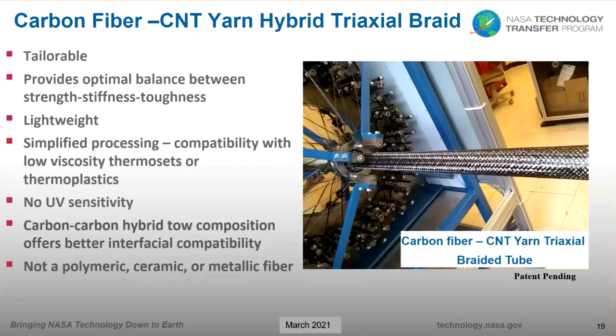My initial concern, my biggest concern with the braiding process, was that the braiding motion and the speeds that we used would cause the individual carbon nanotube yarns to snap off. But that wasn't the case at all. Actually, it turned out to be very difficult to even cut this tube structure from its shape where it's braided onto the mandrel into a flat two-dimensional layer.